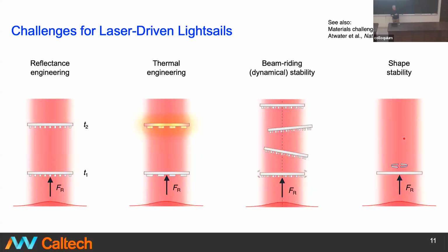But one of the issues that arose as being really challenging to deal with is the stability of the light sail, the dynamical stability. If you take a weakly focused Gaussian beam, as I've indicated here schematically, impinging on a flat surface of finite extent, you can show that it will create a dynamically unstable propulsion trajectory. You will not be able to propel that stably along the optical axis.